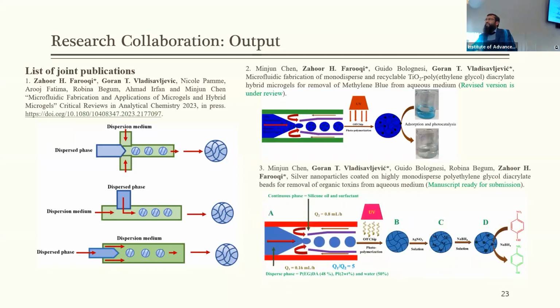We have also fabricated polyethylene glycol diacrylate beads, and we used these beads as a microreactor to fabricate silver nanoparticles in the microgel system. We have used this hybrid system as a catalyst for reduction of 4-nitrophenol and methylene blue present in aqueous medium. This manuscript is ready for submission.